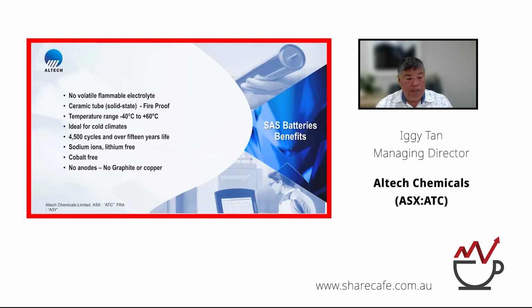Now, the cycle life of the battery: because we don't have a liquid electrolyte, it uses sodium ions, and it doesn't degrade during the charge and discharge process. So the life of the battery is beyond 15 years. Sodium ions are about as reactive as lithium ions; if you look at the periodic table, sodium is just under lithium. So we use sodium ions in the battery. It's totally cobalt free. And the best part of the battery is that there are no anodes. It's a self-forming anode. Because you don't have an anode, you don't have graphite, you don't have copper, etc. So let's go to the next slide.